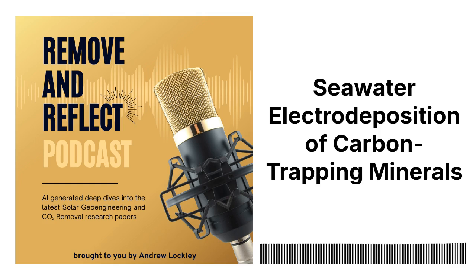So it's like double dipping on the carbon capture. Exactly. You're using the same material to capture even more CO2. That's amazing. And the researchers calculated that an aggregate made up of a 50-50 mix of magnesium hydroxide and calcium carbonate could theoretically store a significant amount of additional CO2 through this process. Wow. And did they actually see this happen in their experiments? They did. They observed around 80% conversion of the magnesium hydroxide to hydromagnesite. So it's not just theoretical. Nope, it actually works. That's fantastic.